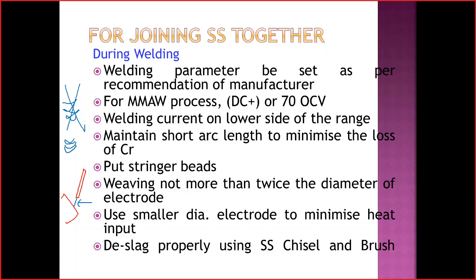Likewise, you have to do welding. Weaving should be not more than twice the diameter of the electrode. Even though weaving will be done, you should not cross more than 2 times the diameter of the electrode. And only smaller diameter electrodes should be used. Normally in conventional welding also we use smaller diameters only. Here also you have to use smaller diameter only.